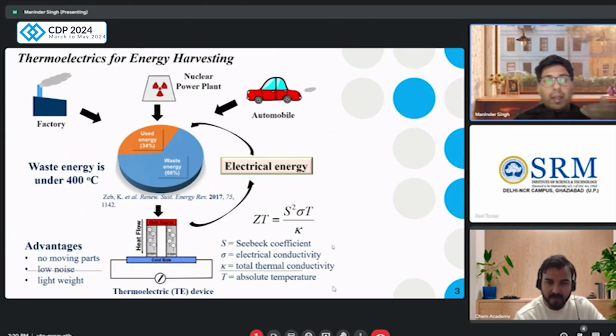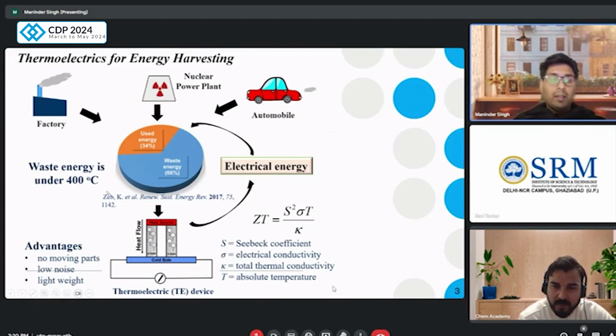Most of the waste energy is under 400 degrees Celsius, and this much heat, 400 degrees Celsius, is enough to create electrical energy. So we created a device which can convert the waste heat to electrical energy using a thermoelectric device, as you can see here. This thermoelectric device works by conduction of electron flow from the heat source to the cold side. So it creates a potential difference across.